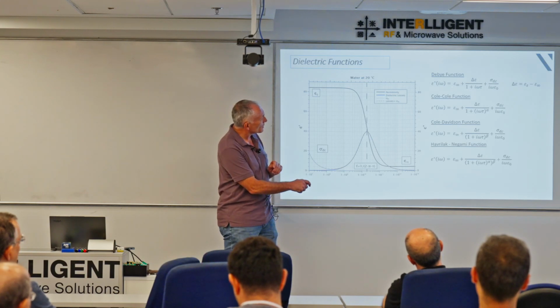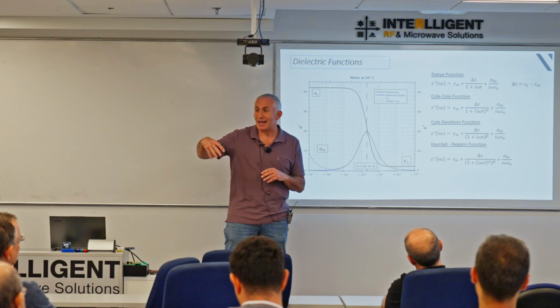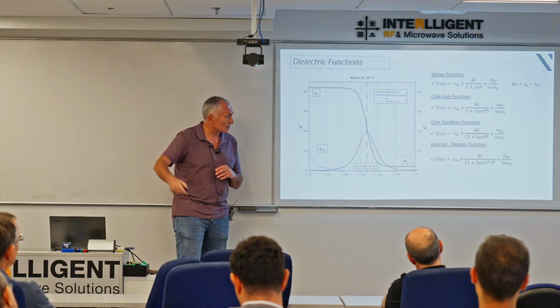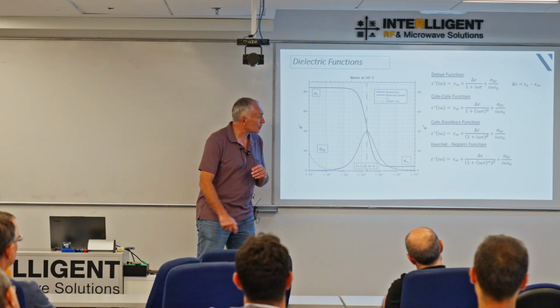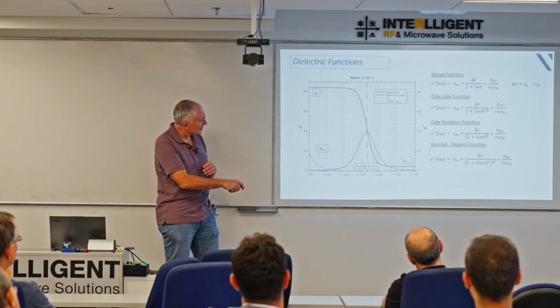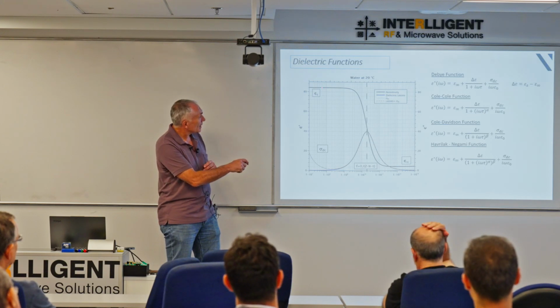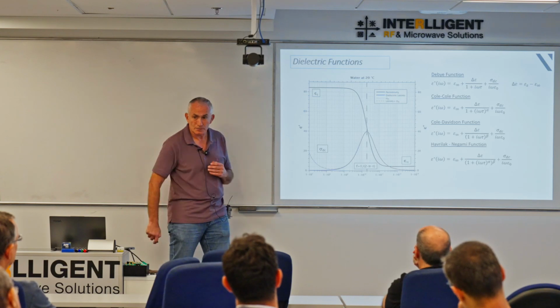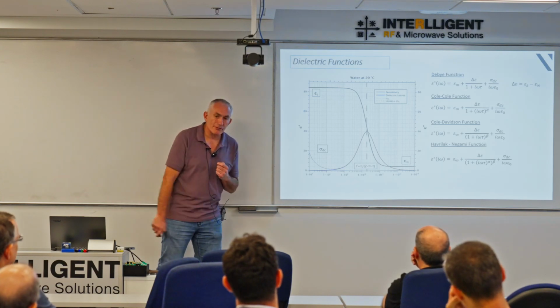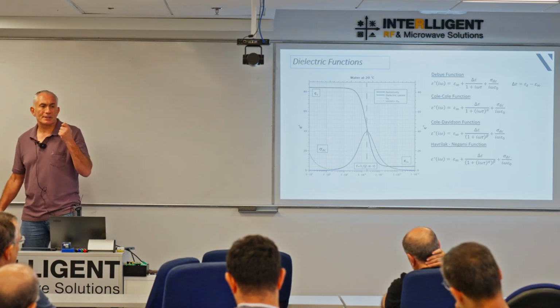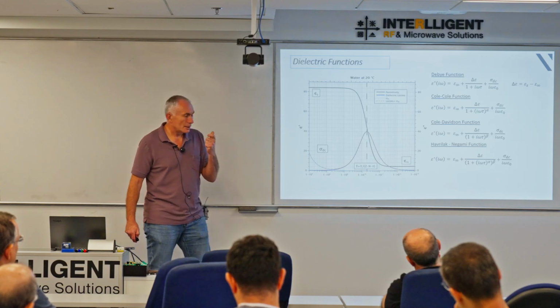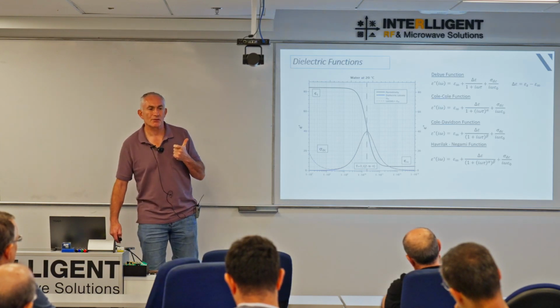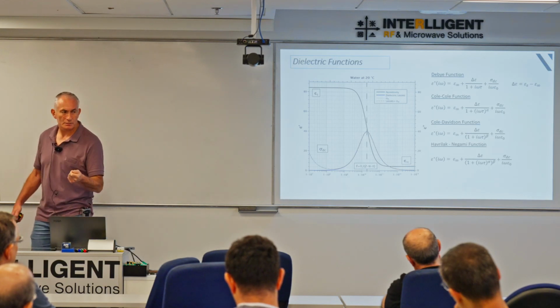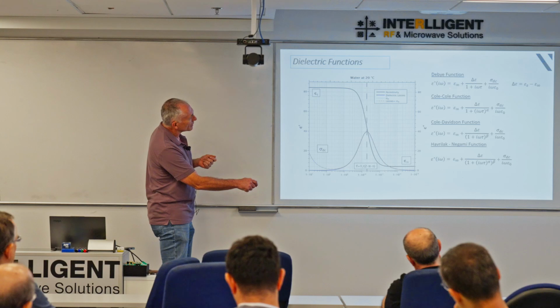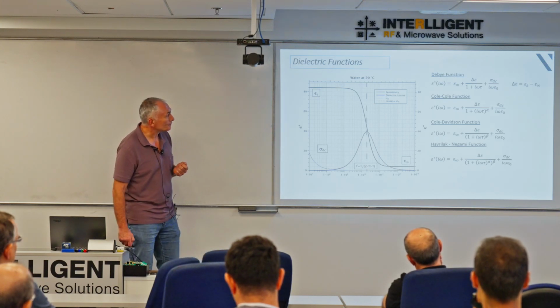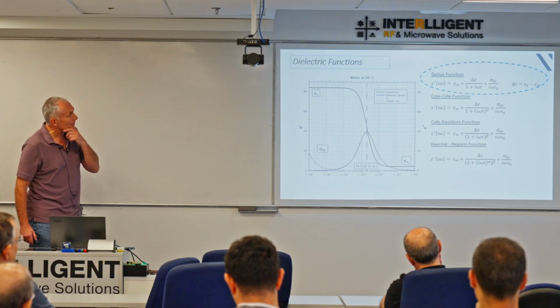You've got high frequency components, basically the residuals of whatever's outside your measurement window, which are going to give you this tail. You've got a dielectric strength, which is the difference between the high frequency residuals and your steady state solution. You've got a particular characteristic frequency, which represents the optimal position for absorbing energy by that material. Which field will it take best of all? And this is all summed up in this particular behavior, which is really a Lorentzian in its form. So that's the Debye function.